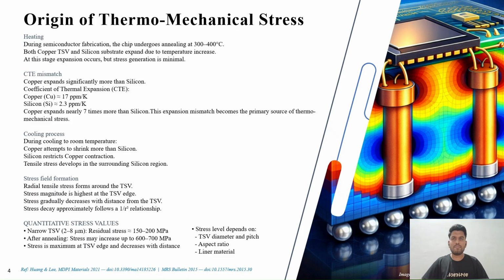Now let's understand the physical origin of thermomechanical stress in TSV-based 3D ICs. During fabrication, the chip undergoes annealing at around 300 to 400 degrees Celsius. At high temperature, both copper TSVs and silicon expand and stress generation is minimal. The problem arises during cooling. Copper has a coefficient of thermal expansion of about 17 parts per million per Kelvin, whereas silicon has only about 2.3. This means copper expands and contracts nearly 7 times that of silicon.